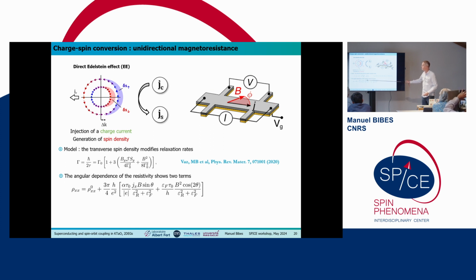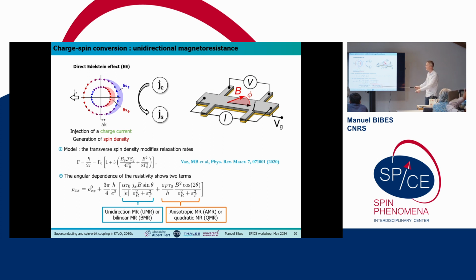It is going to have a unidirectional dependence. Okay, it's going to be unidirectional with the magnetic field in the plane. That's why you have this sin theta dependence. And it's going to be proportional to the Rashba coefficient alpha, to the current, and to the magnetic field. That's why it's called a bilinear magnetoresistance, because it's linear with the current and the magnetic field. And there is also this additional term, which arises because of scattering in between the 2 contours of the Rashba split bands.